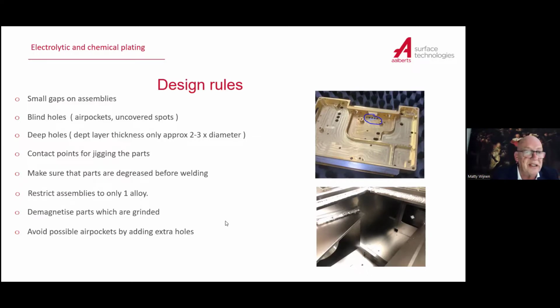Parts which are ground have to be demagnetized, because due to the grinding they become magnetic. And when they are magnetic, they pick up all the metallic or steel particles which are in the complete pretreatment. So you start with a nice part, and when you go into your bath it ends up with a lot of particles on it, which makes it very rough.